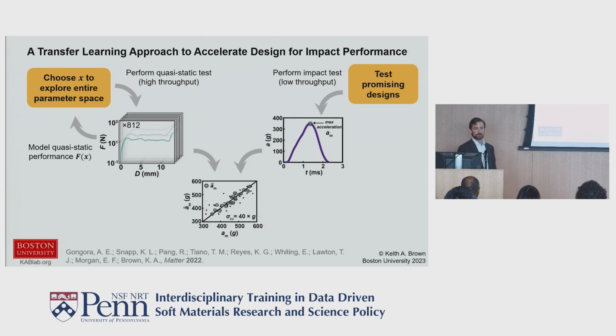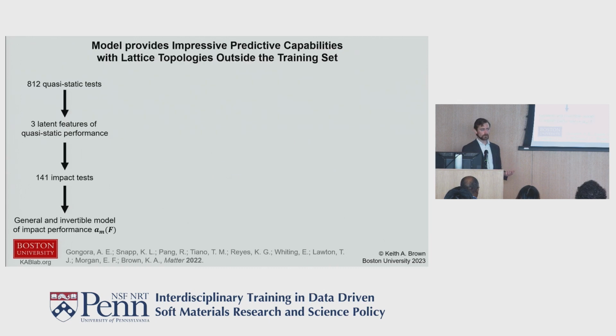And this allows us to build, and this is really the important part, a measure of how the impact performance is dictated by the forces we measure in quasi-static. Because that means we can design things without doing the complicated experiment. In practice, we do about 700 or 800 quasi-static measurements. We use unsupervised learning techniques to boil this down to 3 parameters that we can use to describe any given force displacement curve. We then use those 3 parameters along with our 140 impact tests to build a model that allows us to predict impact performance generally.